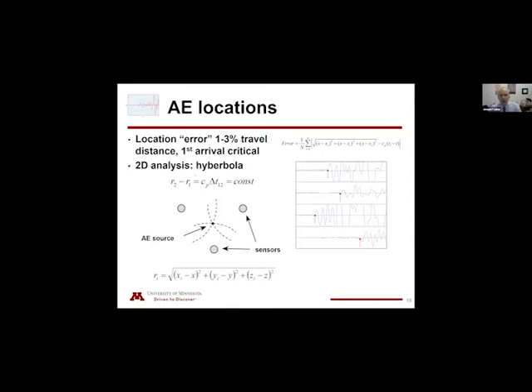So in terms of the 2D analysis, we can construct hyperbola. So this is a parametric equation for a hyperbola. Delta T subscript 1, 2 is simply the relative arrival time between 2 sensors. So again, I'm showing a time history that's recorded from one event on 4 channels. And the red arrow indicating the first arrival of the event associated with the P wave. So channel 1 in reference to channel 2 has a difference in time that we can measure, and that's the delta T that would be used in computing the characteristics of this hyperbola. And of course, we do that for a number of events, and where those cross indicates the location.